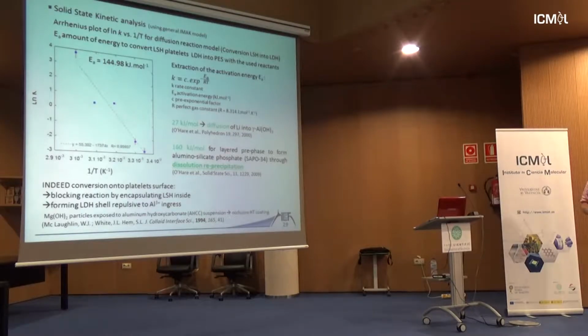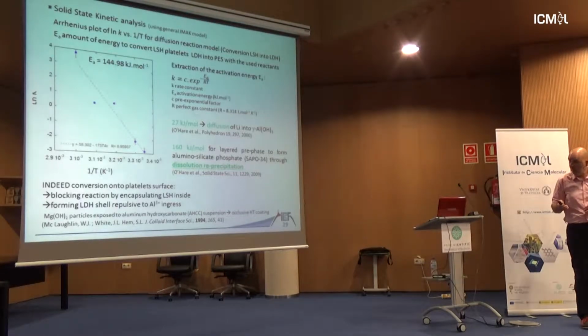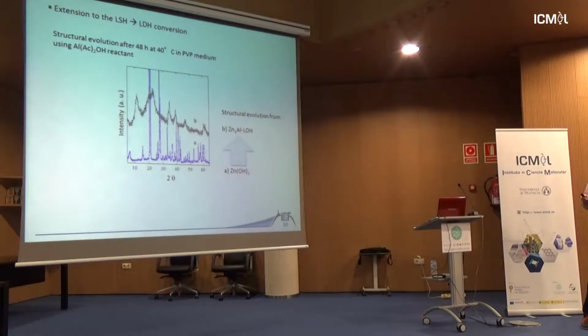So you have to dissolve and reprecipitate again, because otherwise it will form LDH that is repulsive to aluminum ingress. And it has also been mentioned in this kind of formation, inclusive of hydroxide, in another phase, hydroxycarbonate. I will stop here for that. A nice thing is that we can generalize that.